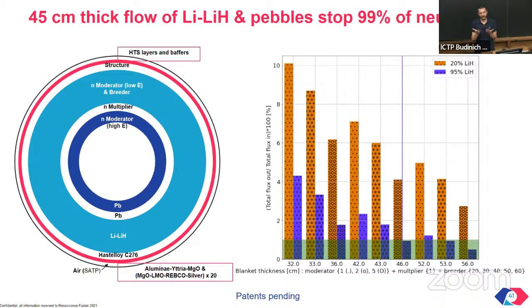We are asking, or other people are asking, one material to do two different jobs, but this material is only good at one and not at the other. So there is a reason why they use water in fission reactors, hydrogen. Protons have comparable mass to neutrons. They are much better attenuators by collisions compared to lithium. In fact, they have a cross-section 80 times higher than lithium. So they are 80 times better than lithium at slowing down these neutrons.